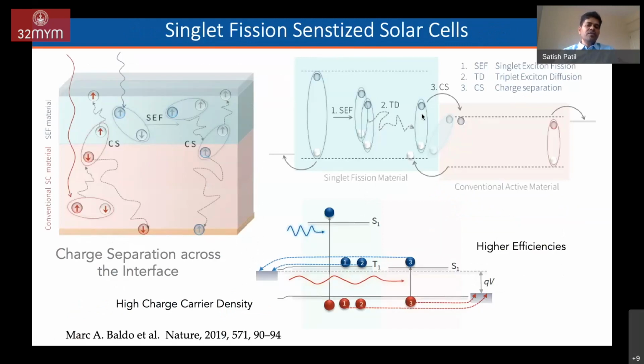This is called singlet fission sensitized solar cells. What are singlet fission sensitized solar cells? I will describe the device structure here. You have a conventional semiconductor material like silicon, which will take the photons at the low band gap energy around 1 eV. But if you coat a singlet fission dye on such a semiconductor, you can take the high energy photons and reduce the losses. And this dye, where my cursor is pointing, has the property that it can undergo fission. Then you can really improve the total quantum efficiency. But there are many challenges here.